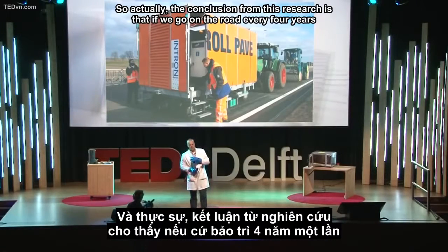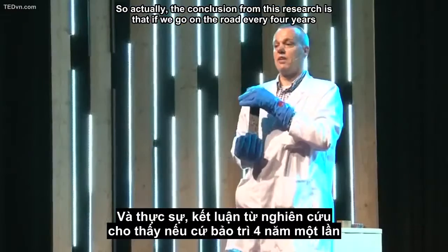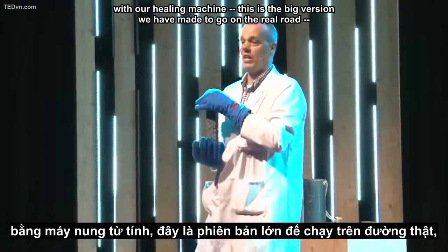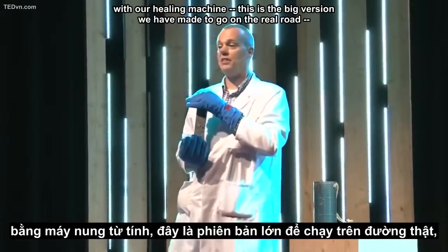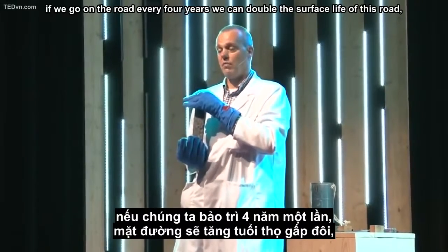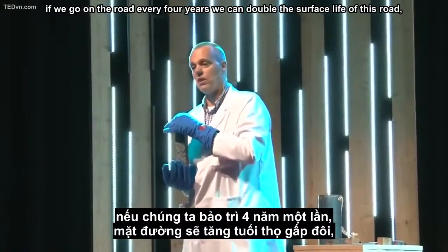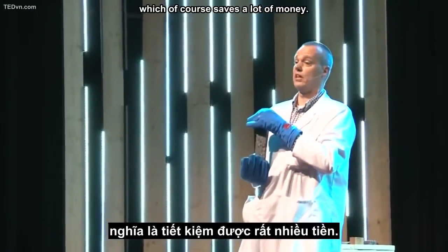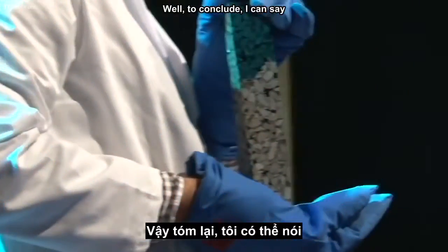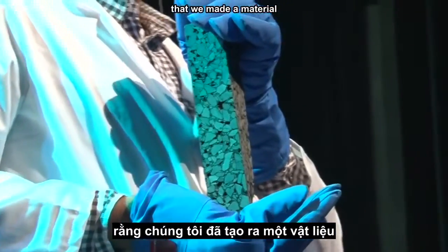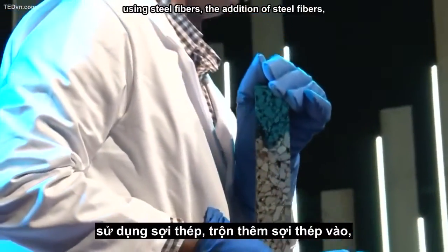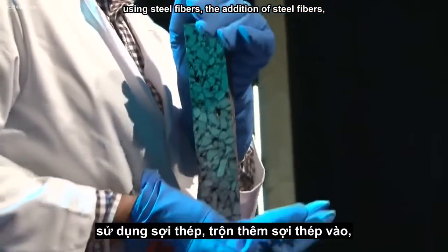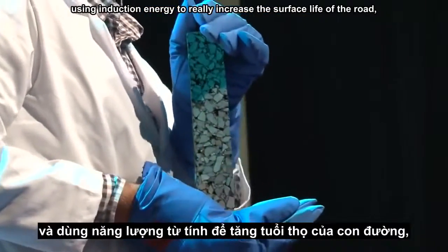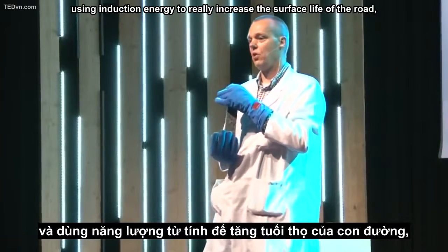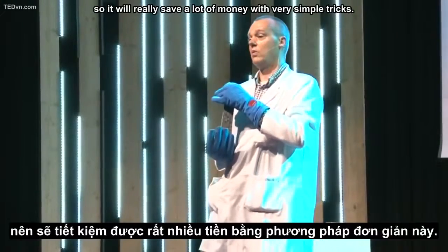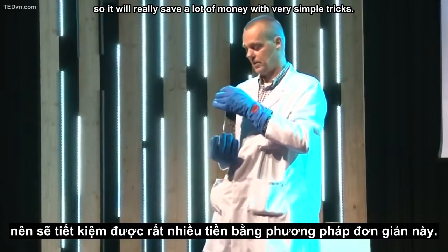So the conclusion from this research is that if we go on the road every 4 years with our healing machine, this is the big version we have made to go on the real road, we can double the service life of this road, which of course saves a lot of money. Well, to conclude, I can say that we made a material using steel fibers, using induction energy to really increase the service life of the road, even double it, so it will really save a lot of money with very simple tricks.